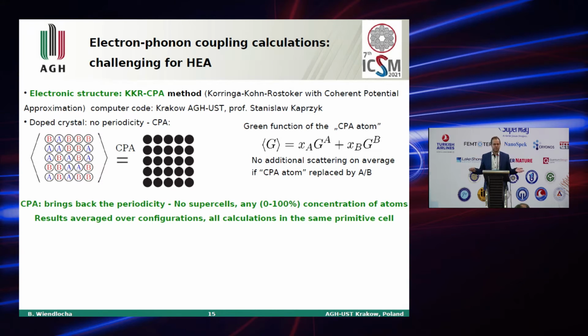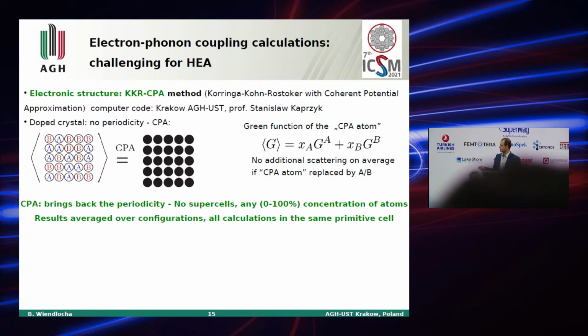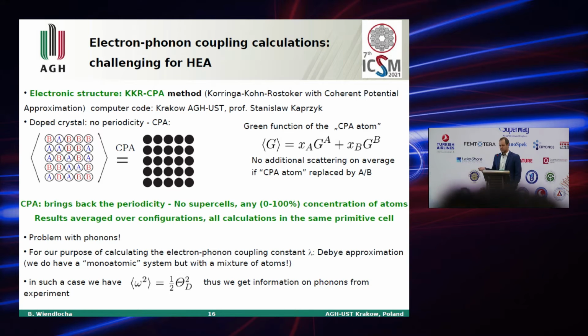We don't have to use supercells. Every result is an average among all possible configurations automatically. So we can deal with any concentration of atoms. And as I said, we have a problem with phonons. KKR-CPA for phonons is not developed, so in this work we approximate the phonon spectrum using the Debye approximation to get the omega square parameter, and the Debye temperature is taken from experimental measurements.